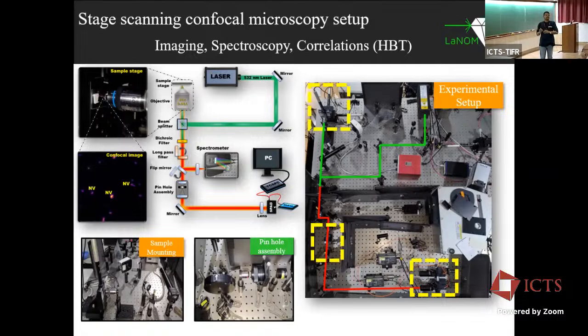Okay. So having this 6, 7 Purcell enhancement is still a good number compared to the ease of fabrication of the samples and experiments. But the state of the art, Purcell enhancement with these photonic crystal cavities, some papers I know of have an enhancement of around 100 or so. Yeah, I agree with you. But the amount of effort you have to put in to make a 2D photonic crystal cavity and then get an effect like that, compared to that, our proposed system will be much easier to do.